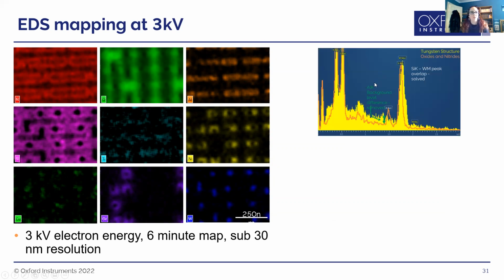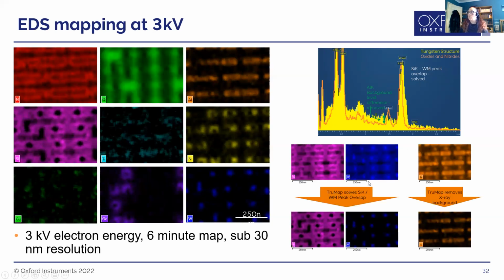What we have to do in the software is make sure that when we're looking at some of these light elements, that the peaks aren't overlapping. And that's quite common with the light X-rays or the low energy X-rays, is you get a lot of peak overlap. And it's quite important to have the software to be able to differentiate that. And we do, and it's called TrueMap, and you can see the difference here.